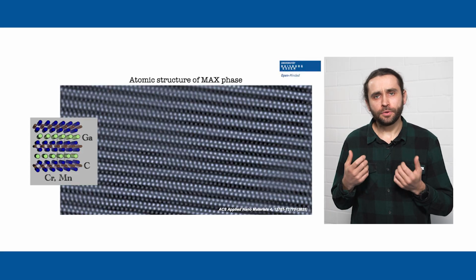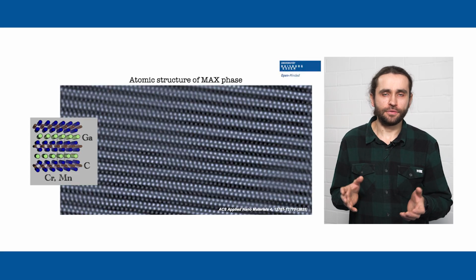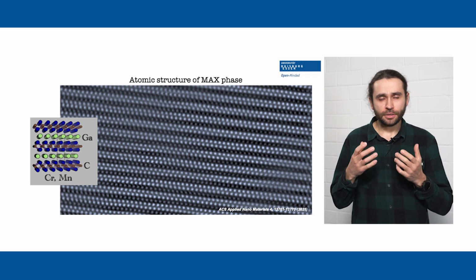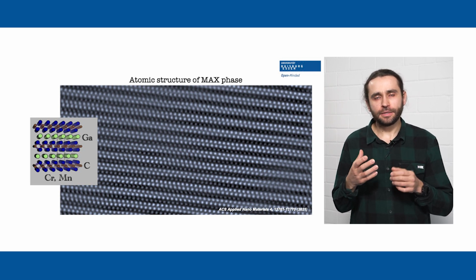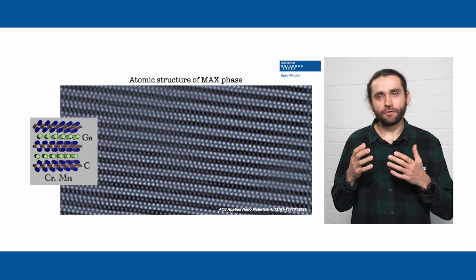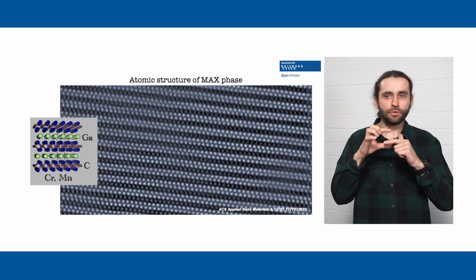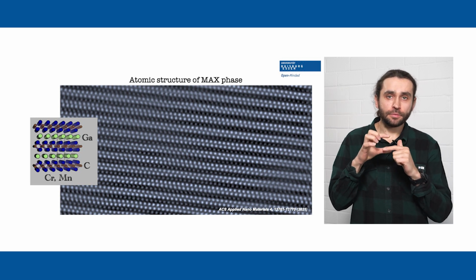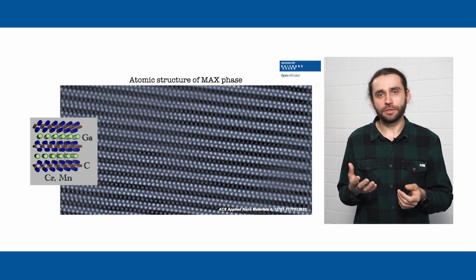Did you hear before of MAX phases? They are inherently beautiful substances made up of carbon and other chemical elements like chromium and gallium. It's important to have at least 3, but many others are possible. So their beauty is an alternative one you cannot find in nature easily. The layer of carbon alternates with a layer of chromium, then a layer of gallium comes, and this repeats until nature allows. Or I can also stop such an intimate process just by terminating a sequence of pulsed laser deposition.